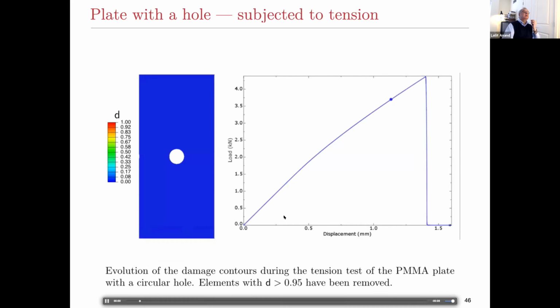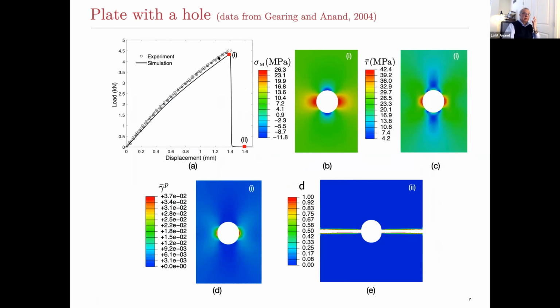So here's a simulation. Crazing happens, it propagates, things fail. That's to be expected. But what is nice is you can actually also predict the load displacement curve quantitatively. That's some actual data. This is a simulation. And again, there's nonlinearity. When crazes initiate, the mean normal stress is about 26, the tau bar is about 42, and so forth.